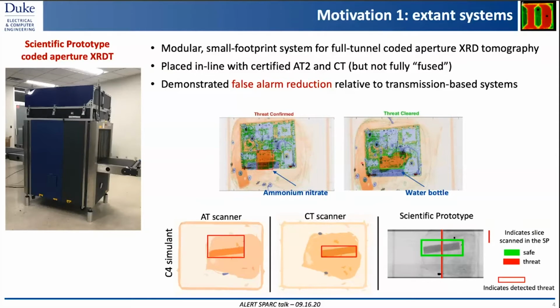So we've at least been able to demonstrate that there are some things that might be difficult for transmission systems that diffraction can do a great job on because of the additional material specificity. In our current program under BA 1402, funded by S&T, we've actually placed this in line with certified AT2 and CT systems. And I make this designation, that I'll come back to in a minute, that we've placed it in line but not fully fused. We haven't fully combined the transmission and scatter systems.